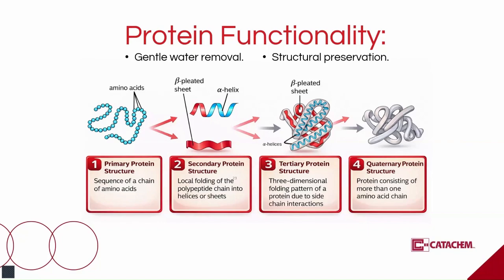Proteins are fragile because their function depends on precise structure. During lyophilization, if shelf temperature rises above the collapse or denaturation threshold, proteins can unfold or aggregate. If you remove water too aggressively without stabilizers, you can disrupt the hydration shell and the matrix that protects conformation. Gentle water removal means product temperature control during the primary drying, a stabilizing excipient system to protect the structure, and secondary drying that achieves target moisture without thermal damage. The output is not just dryness, it is functionality after reconstitution that is the key metric.